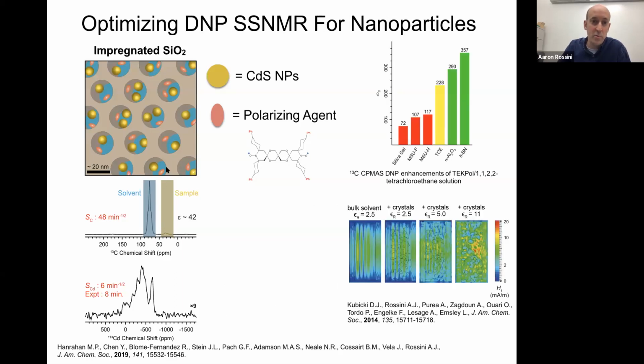Okay, one of the problems with this strategy is that silica is actually not a great material for DNP. What I mean is it has unfavorable dielectric or optical properties for DNP. What we showed in this 2014 paper when I was a postdoc in Emsley's lab is that if you fill your rotor with materials that have a higher real dielectric constant, you tend to get better coupling of the microwaves into the DNP rotor, and that translates to higher DNP enhancements. And so you can see if you do a DNP experiment on silica just impregnated with TEKPol in TCE, we tend to get enhancements of about 100.